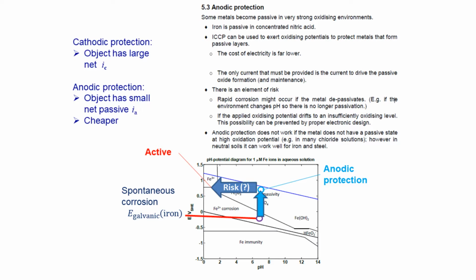This actually has some quite striking advantages, which is because we now have an anodic protection system where the protected iron is passive and anodic instead of borderline immune from corrosion where it would have been a large net cathode. This means anodic protection is potentially much cheaper than applying cathodic protection because we don't have to supply the large current required to balance out the hydrogen evolution which we had on the cathodic protection system.